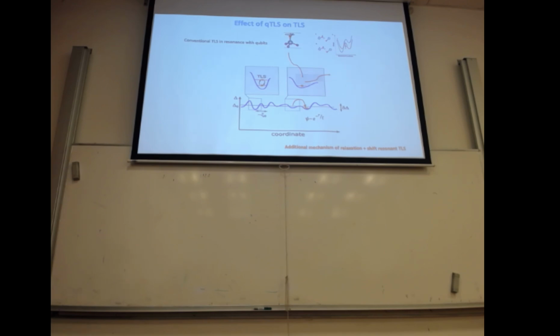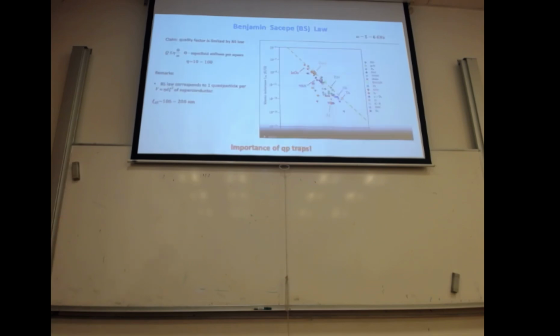From Jürgen's analysis, we saw that if you look at the typical relaxation time of the two-level system, and you assume that it is only phonons, this is not sufficient. There must be some additional mechanism, quasi-particles. This is another possible mechanism that we think can be used, and it can create both relaxation and also a shift of the level system.